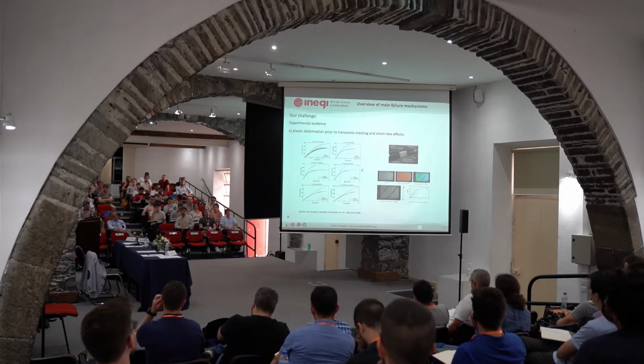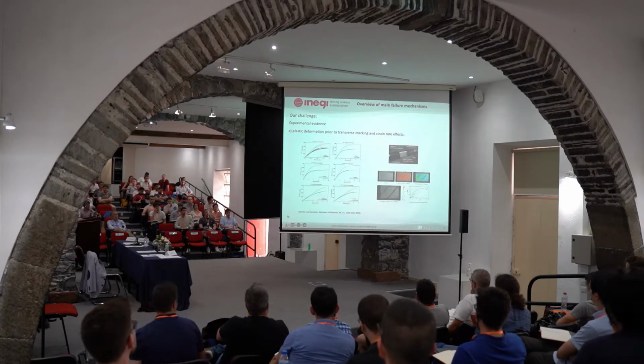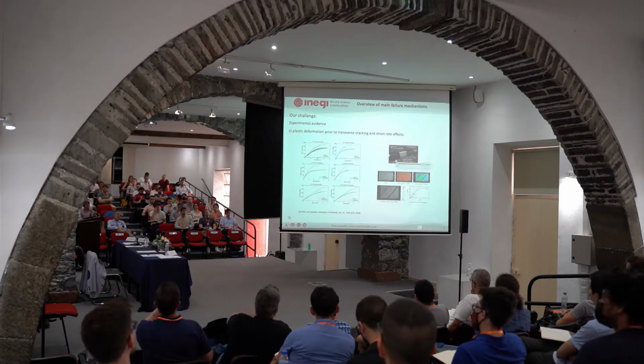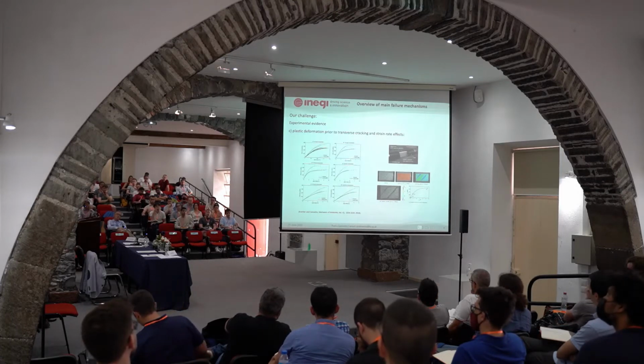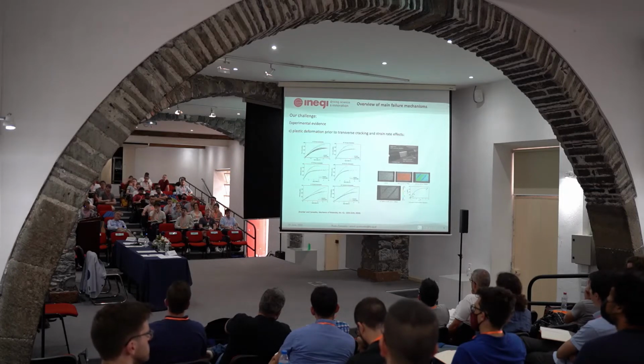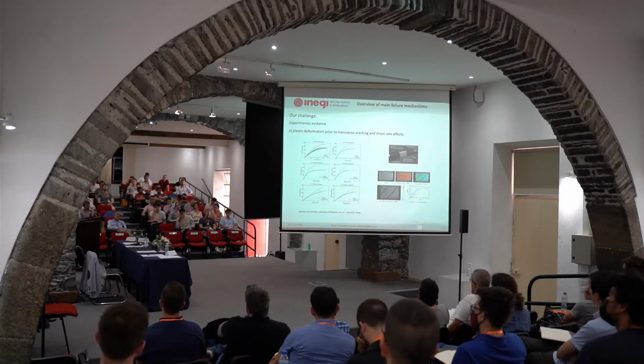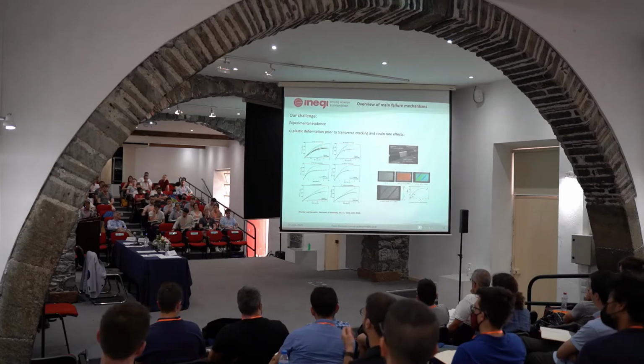Okay? And you can see here, for example, this is just the use of digital image correlation in one of the tests. You can see that we actually had to change completely the setup of the split Hopkinson bar. This is interesting because it relates to what I said before: back in the early or mid-2000s, there was a round-robin exercise in terms of high strain rate testing of composites, and the results were all over the place. Some groups claimed there was no effect, other groups claimed there was one effect going in one direction, and other groups had an effect going in the other direction.